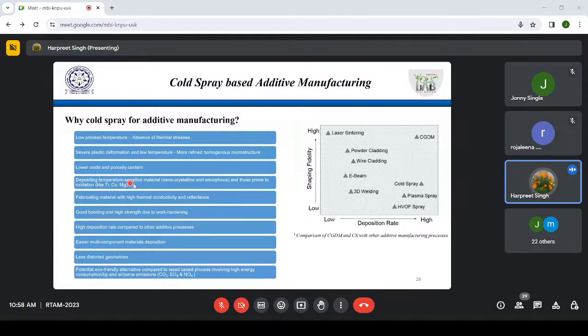Temperature sensitive materials, of course, because high temperatures are not involved here, you will not lose your nanocrystallinity and so on. Fabricating material with high thermal conductivity and reflectance is another challenge. If you talk about laser sintering or laser melting and E-beam, when the material has very high thermal conductivity, there will be the problem of focusing the heat in a localized area. As soon as the laser comes, the heat will dissipate because thermal conductivity is high. Similarly, in laser-based processes, if the material is very reflective, you will not get the heat transferred, right?